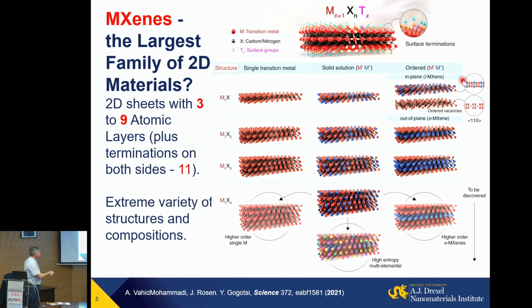We can also make in-plane ordered MXene with alternating atomic columns of different metals. For example, yttrium and tungsten or moly. And if we etch one of them that is more chemically active, like yttrium or scandium, we will end up with materials with atomically thin trenches of vacancies here. So I think you get the idea. We can really do nowadays atomistic engineering of two-dimensional materials. We have an almost infinite number of compositions in a variety of different structures created. And this is the beginning only. People make nowadays two-dimensional borides, silicides, more complex structures, and I'm sure even further interesting arrangements of atomic layers.